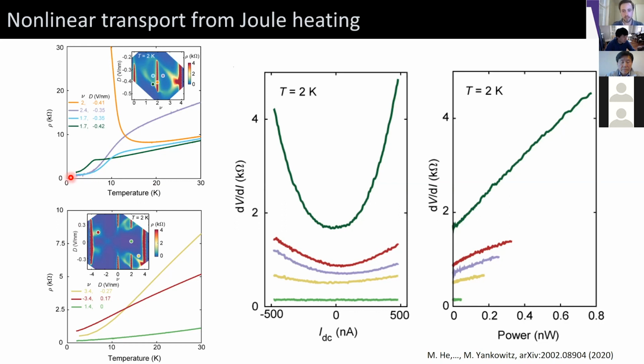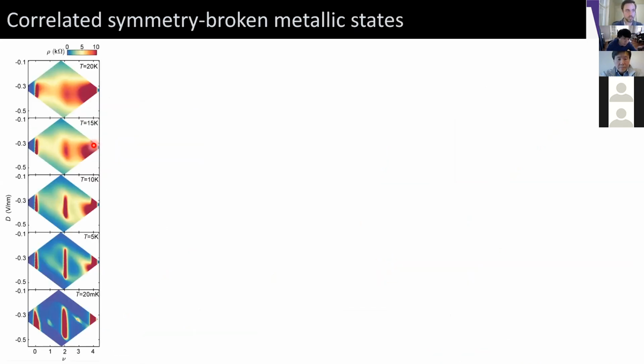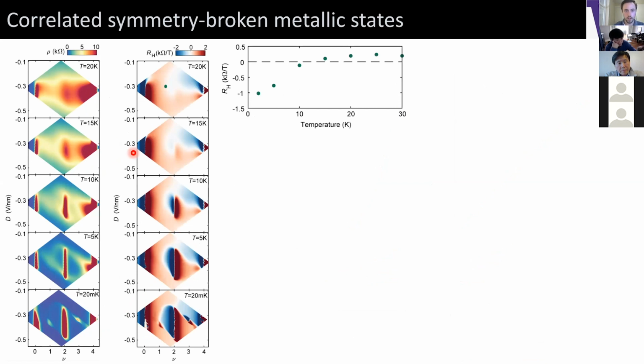So instead, our understanding is that these sharp downturns are really a consequence of spontaneous symmetry breaking of these bands as a consequence of developing correlations as we cool the system. We can illustrate that a bit better by taking zoom-in maps of the device resistivity around this halo-like region. And as we warm the system, we see that this halo collapses into this broadly resistive stripe at high temperature. This is a bit confused by thermal activation to remote bands, so we can look at this in the Hall coefficient instead. And here we get a sharper measure of this halo-like region, which is basically traced down in white. And what we see is that this halo-like region collapses towards half filling as we raise the temperature of the system and eventually disappears.